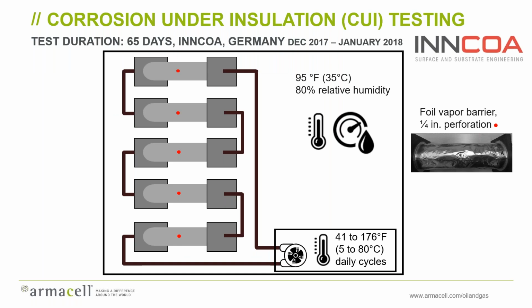We were so interested by corrosion results that we commissioned Incoa, which is an independent surface substrate engineering company who specializes in corrosion under insulation, to run some tests. And what they did, they put an environmental chamber, which they set at an elevated temperature and humidity, 95 Fahrenheit and 80% relative humidity. They put some carbon steel pipes in, they connected those in series and flowed through them fluid ranging at temperatures from 41 to 176 Fahrenheit, changing daily. So in other words, a daily cyclic episode.